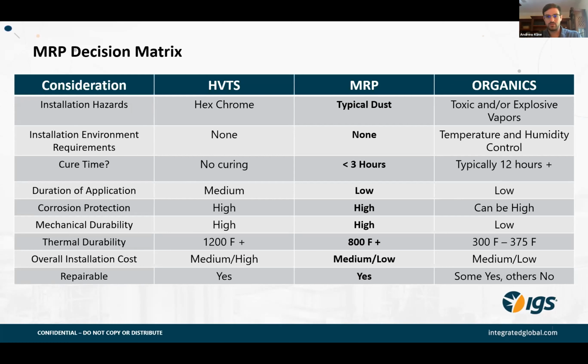The interface between the HVTS zone and the top coat polymer is interlocked. So it's very close and dense, but you lose that ability of that corrosive media to impregnate its way through. So even as it impregnates into the polymeric layer, that interface zone stops it because that base substrate is non-reactive. So it's not even corrosion resistant. It's that coating doesn't corrode.